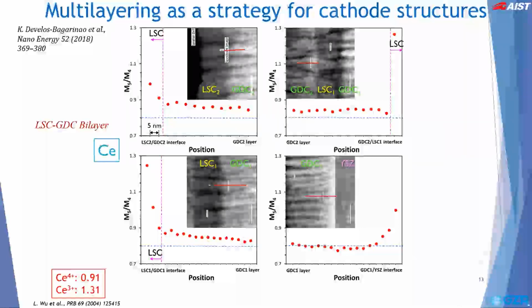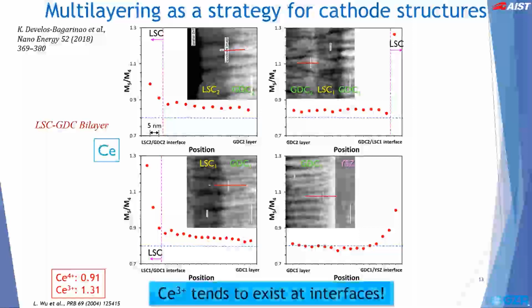Interestingly, this result suggests that there is a tendency for the existence of reduced cerium near the vicinity of the interface with the LSC layer. The presence of cerium 3+, on the other hand, suggests the existence of oxygen vacancies along such interfaces, which can be considered as active sites for oxygen incorporation.